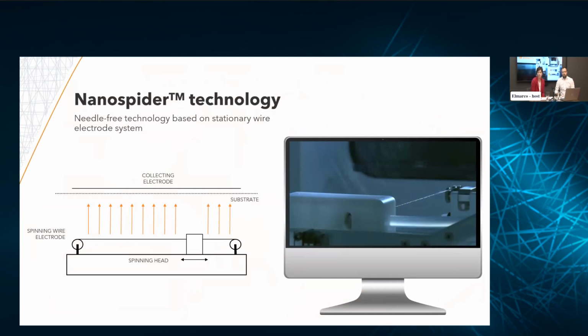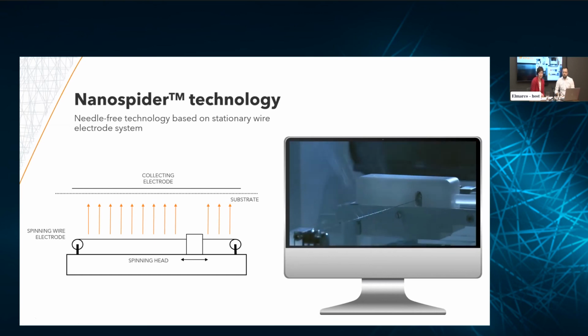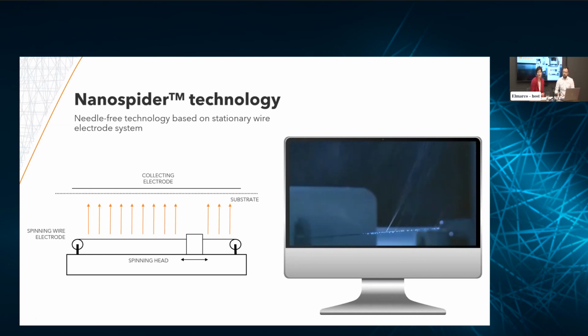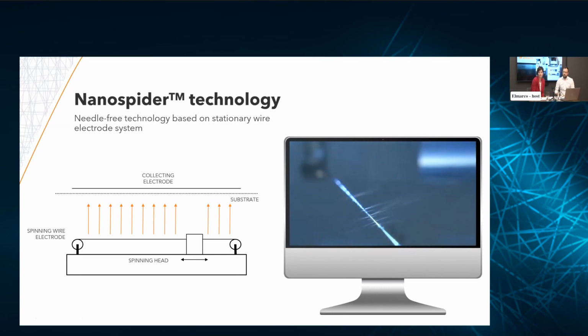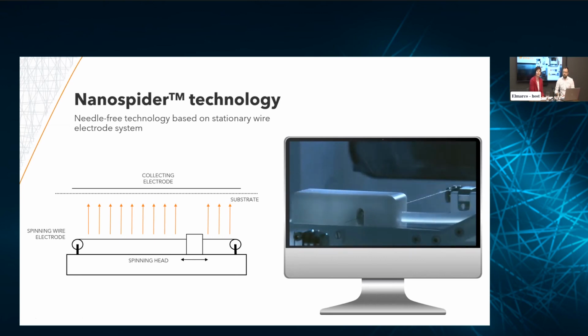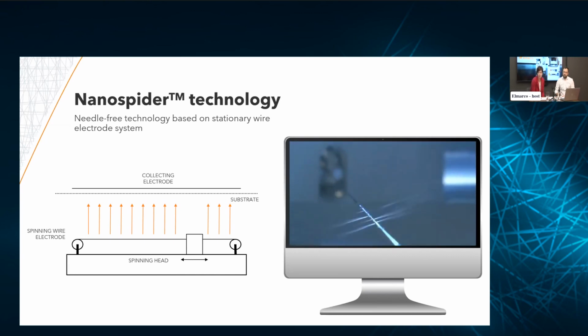Briefly, on how this technology looks like. We have two electrodes, where on the spinning electrodes we are depositing the polymeric solution by the moving carriage, as you can see on the short video, and the fibers are generated towards the collector, which is again the wire. We are coating a moving substrate, which can be any kind of non-woven textile or paper or any other flexible material, which is rewound through the spinning chamber. And by that, we can provide a two-dimensional coating, or surface coating, of the substrate.